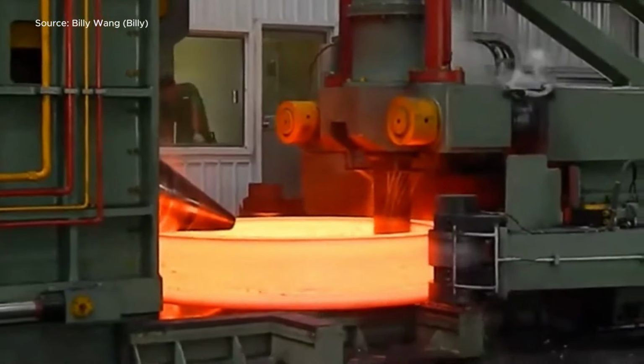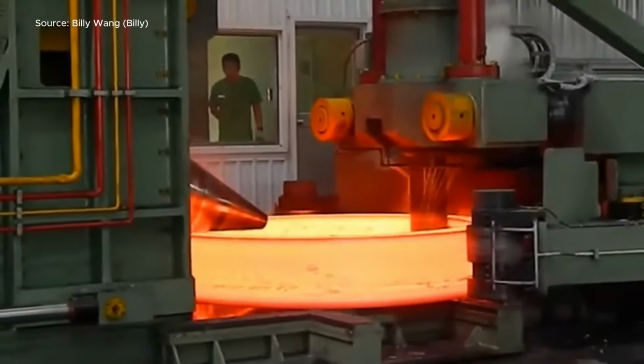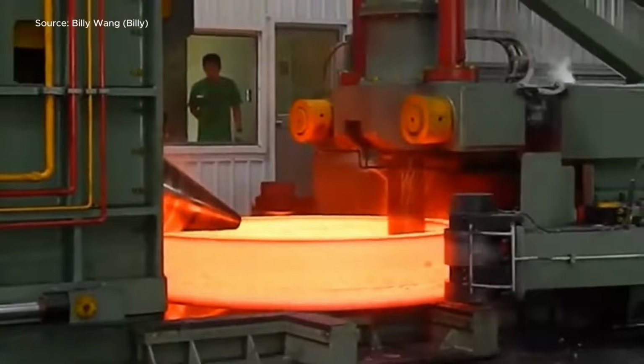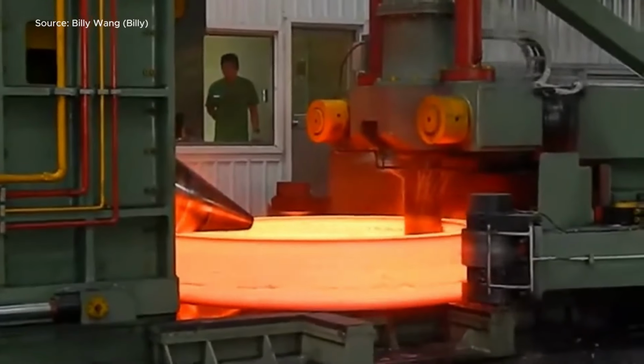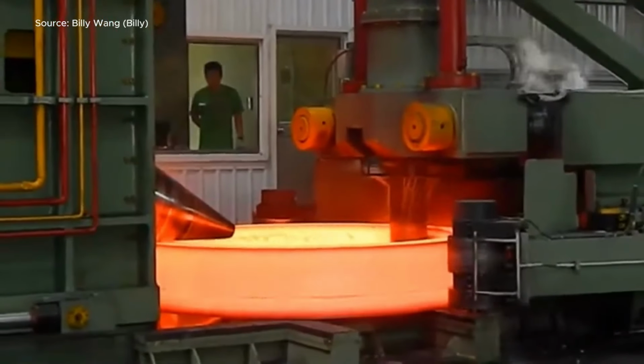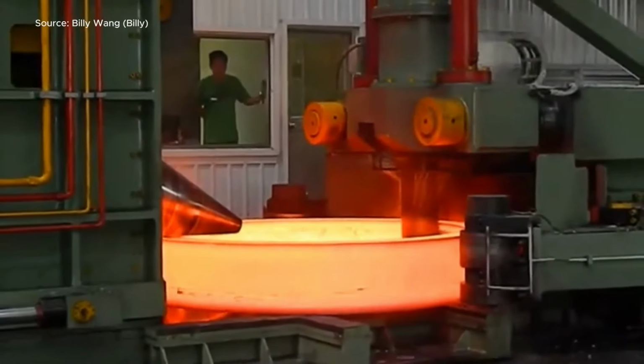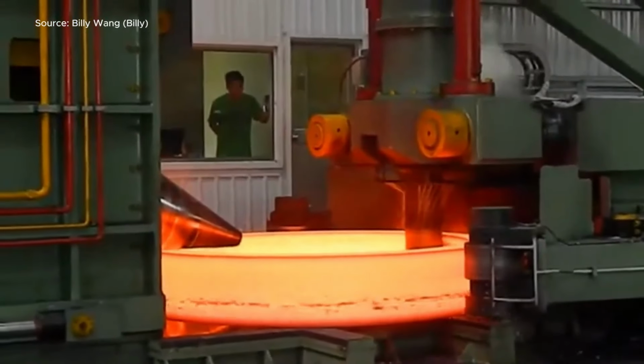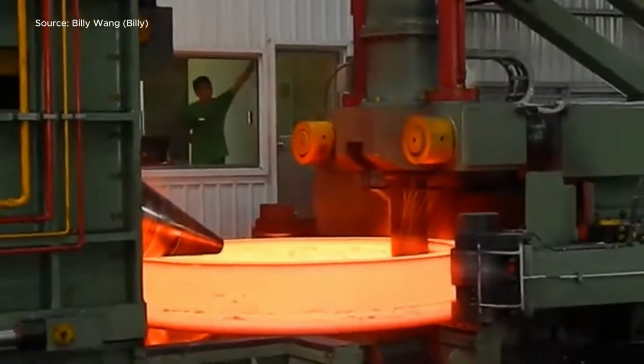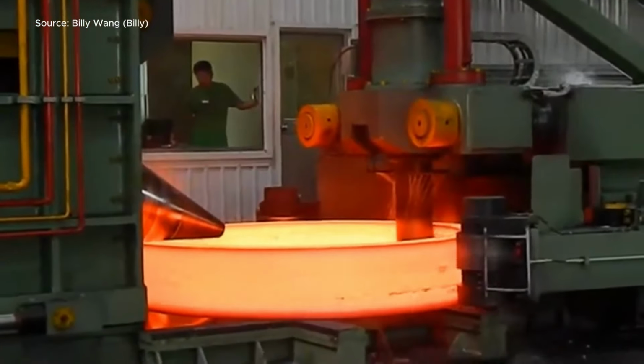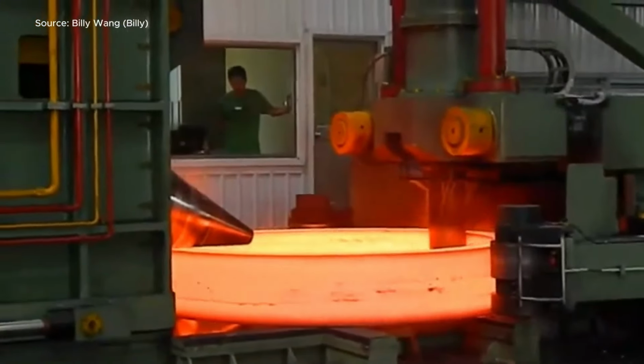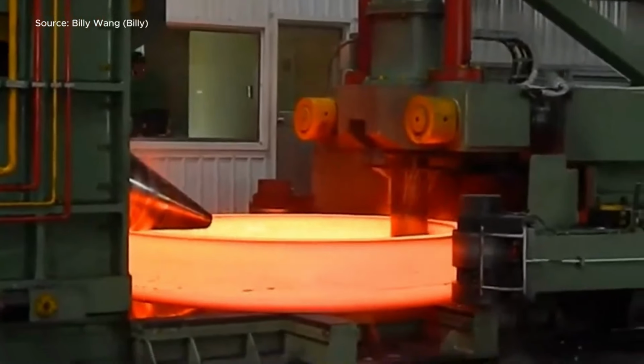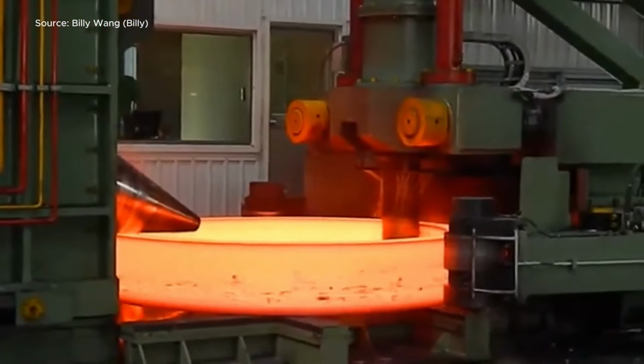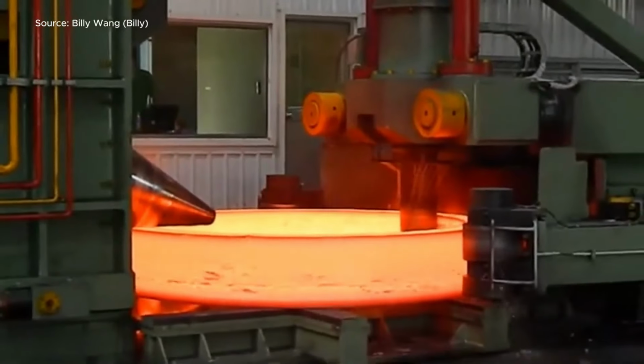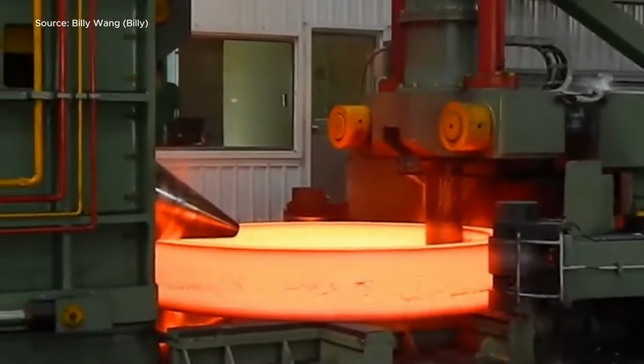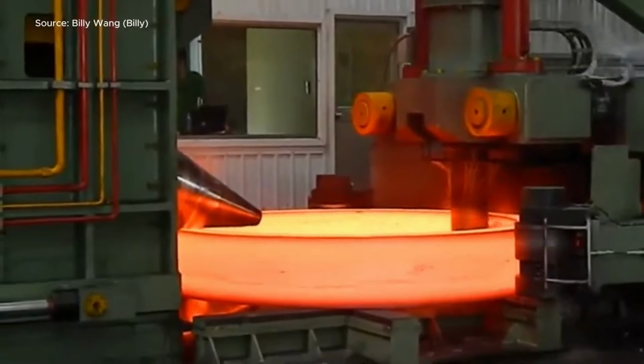This dual-axis rolling ensures uniform material flow, precise dimensional control, and structural integrity throughout the forging. The D53K machine utilizes hydraulic force, delivering up to 8,000 kilonewtons of pressing power. It accommodates ring diameters ranging from 350 millimeters to 8,000 millimeters and heights from 60 millimeters to 800 millimeters. Rolling speeds vary between 0.5 meters per second and 1.3 meters per second, depending on the material and desired ring